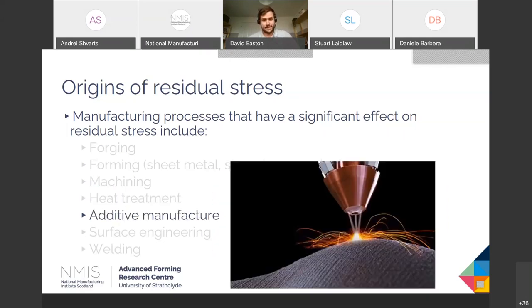We have heat treatment, additive manufacture. So this is another great example of where residual stress has to be considered in the manufacturing process. Additive manufacture is a very exciting technology. We can quickly and efficiently build complex parts that would take much longer or be much more expensive to do otherwise. But because of the nature of the process, we are introducing high levels of heat, quick cooling, and that's inevitably going to lead to residual stress. So if we're not careful and we don't consider the effect this is going to have on residual stress, then although we get the shape we want, we might not get the performance, compared with a conventionally manufactured part. So residual stress plays a big role when we're considering additive manufacture.